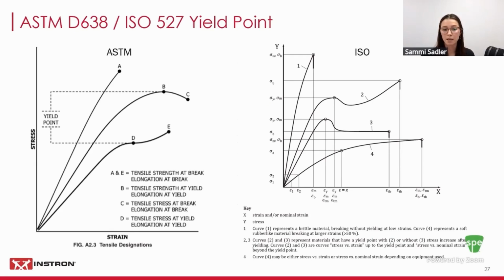If a specimen yields, the nominal strain calculation must be used from then. That means from the beginning of the test up until yield, you will need your extensometer. And then once that material yields, the extensometer must be removed and nominal strain will be used from then on.